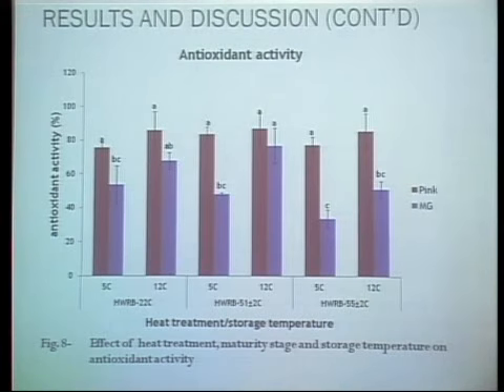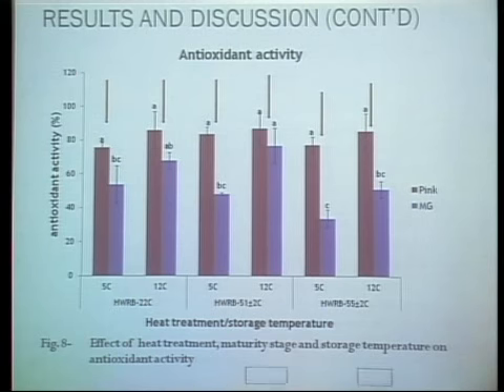Now for the antioxidant activity, we also noticed that the heat treatment, the maturity stage of the fruit, and the storage temperature also had an effect on the antioxidant activity. But most importantly, we noticed that most of the heat treated fruit, even though there wasn't any significant difference, had a higher antioxidant activity, especially at this storage temperature, which of course was not different from the control at 12.